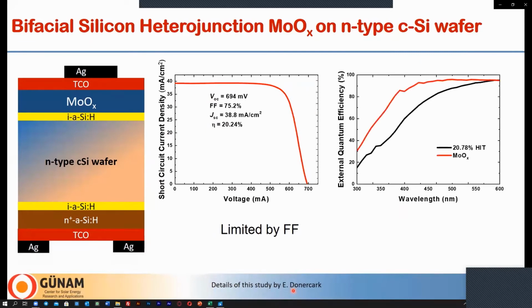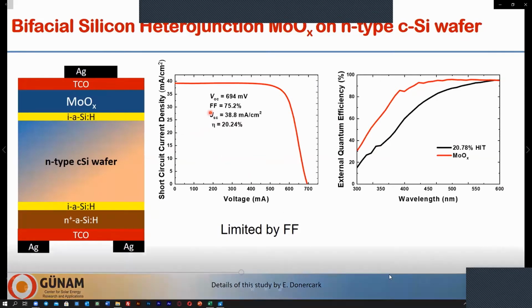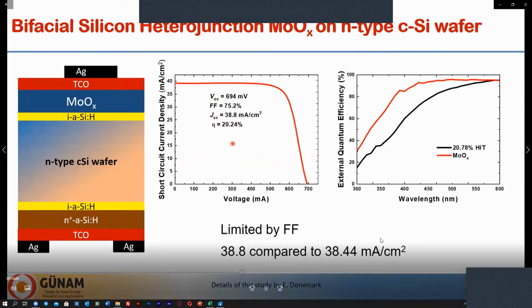The important point here that I want to make is the excellent EQE response in this portion of the spectrum up to 600 nanometers. So in black, we have the EQE for a 20.7% heterojunction solar cell fabricated with almost the same parameters for the backside and the passivation. And the cell with molybdenum oxide has attained a higher JSC of 38.8 milliamps compared to 38.44 milliamps.